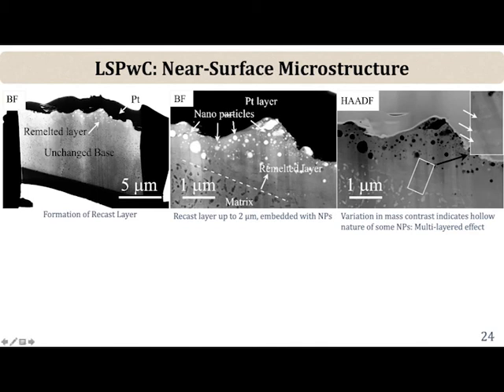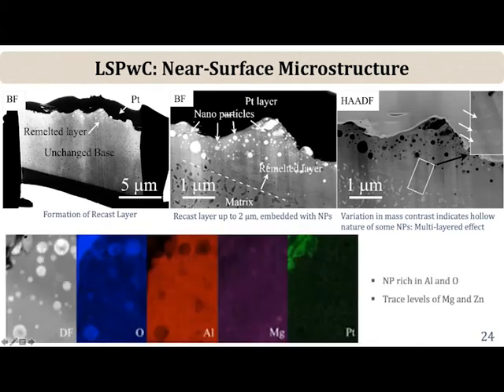But you have a remelted and recast layer, and in this layer you see some very interesting features. So you have what look like nanoparticles. These appear relatively dark in this high angle annular dark field image, suggesting that they are actually enriched in oxygen. So these are oxygen-rich aluminum nanoparticles. Some of them could also be hollow. Some of them could simply be voids or bubbles, clusters that have just collapsed. But what we could show is that these are principally rich in aluminum and oxygen.